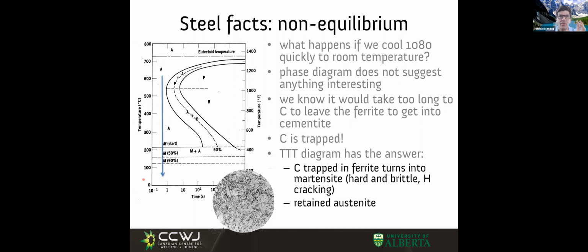In that case, the carbon has no escape. The carbon lives a very unhappy life inside the ferrite, and the ferrite lives a very unhappy life with the carbon inside, and it's all deformed. It goes from being BCC, body centered cubic, to BCT, body centered tetragonal. And now it's not so easy to deform because all the slip planes are all wrong, and it becomes very hard. That's martensite, and it's very hard and very brittle because you cannot deform it.